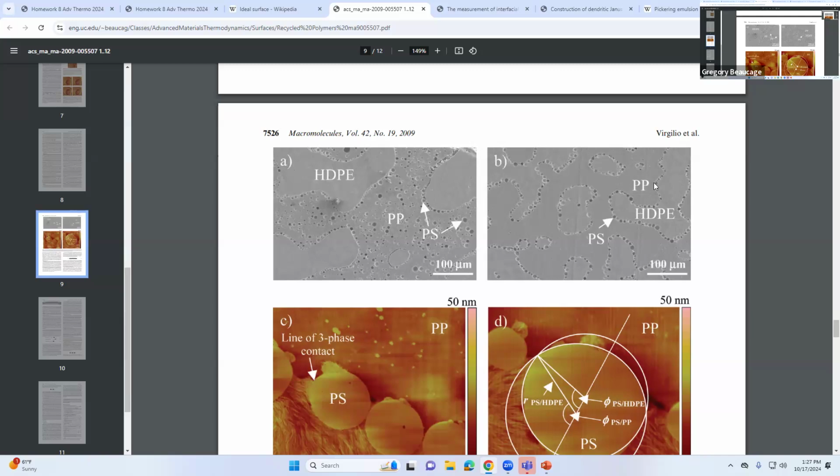He says you can predict just from the ternary spreading coefficients, the lambdas, that you would get polystyrene near the high density phase and polystyrene near the polypropylene phase if you have this other component in it. So he predicts all the things that you observe, from the ternary numbers, but he doesn't actually predict the quaternary. He doesn't have a cartoon of how that happens.